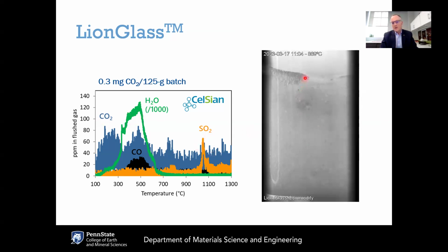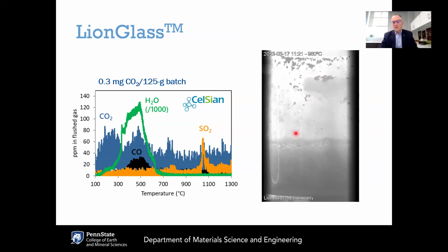Now, if you look at the movie here on the right, even by the time we got to 800 degrees, you could see some pretty rapid reaction kinetics happening with melting. As we get to 900 degrees, this looks a lot like how soda lime looked at 1400 degrees C. And now as we get to 950 degrees C, the bubbles are coming out and we get a nice homogeneous glass. And in fact, one of the cool things that we're able to do with LionGlass is to push the liquidus temperature below 950 degrees C. And so you can see here that at 1,000 degrees C, it's a really nice quality melt.